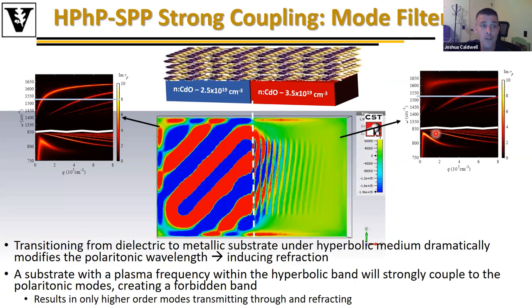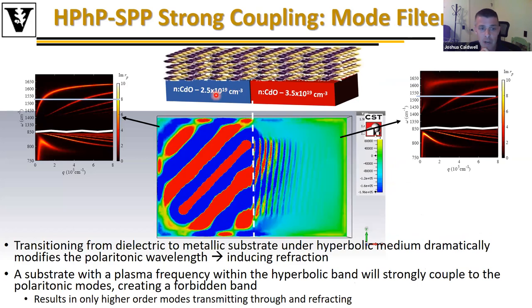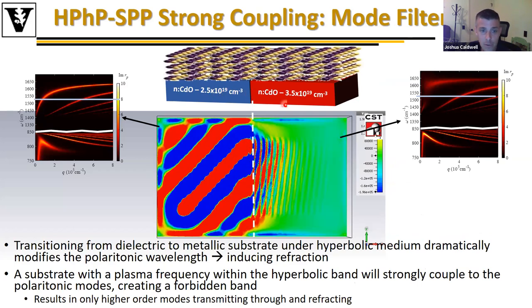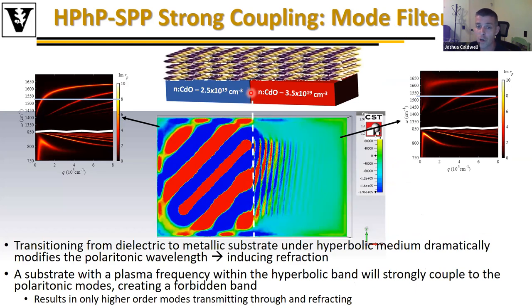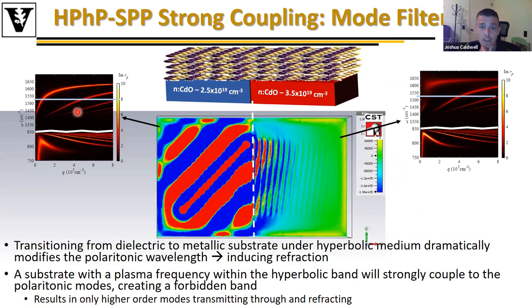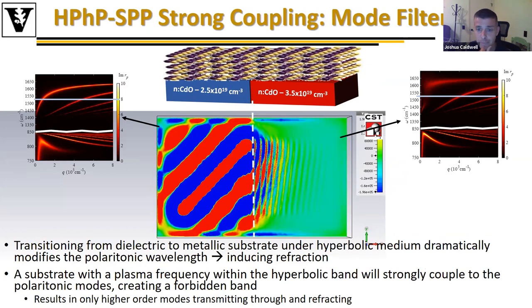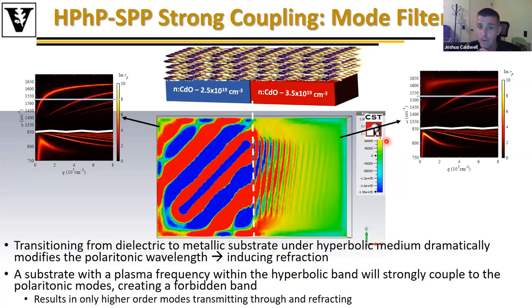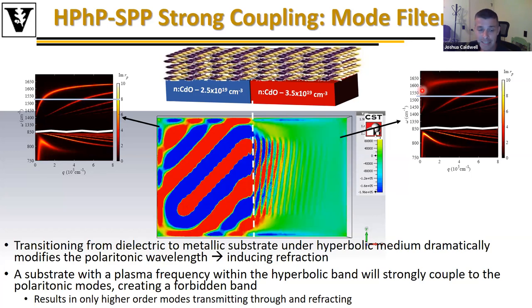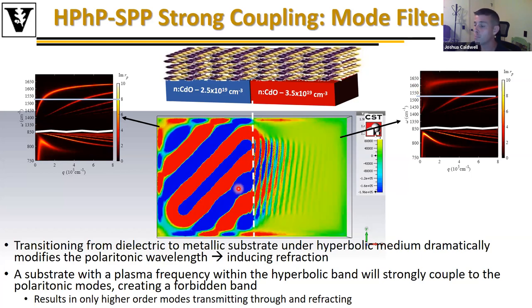First, we have now been able to demonstrate that using cadmium oxide, if you have a separation between two different carrier densities, here, the left-hand side is a mode where the plasma frequency is below that of the upper Reststrahlen band of boron nitride, so leads to this dispersion shown here. The right is one where the plasma frequency is inside that. We actually end up with a strong coupling phenomenon between these two modes, which causes a band where the fundamental mode cannot be supported. And thus, I can stimulate the mode within the left-hand side, where cadmium oxide is behaving like a dielectric, but that fundamental, first order mode cannot propagate across and refract across that interface, leading to a modal filter that could potentially be realized within these structures.